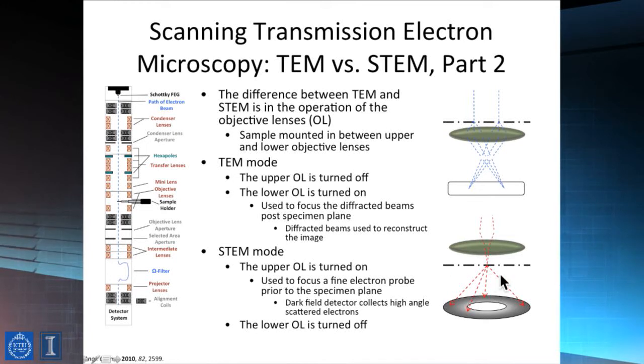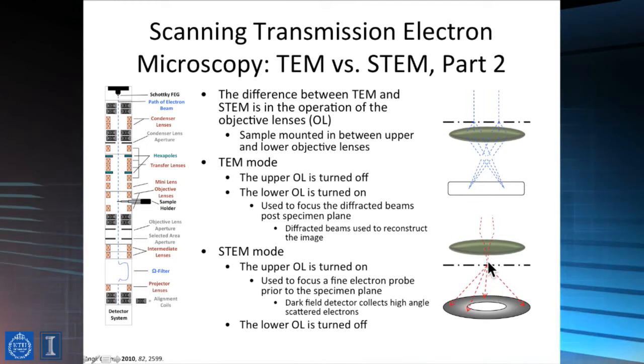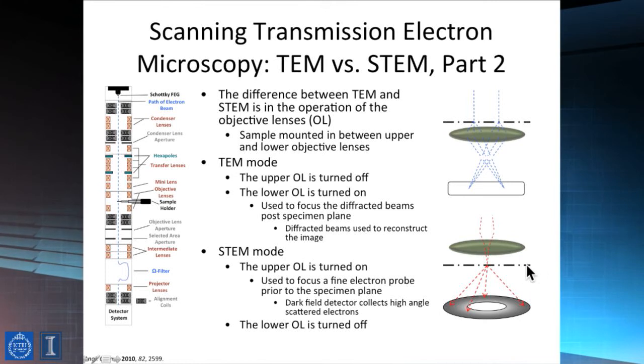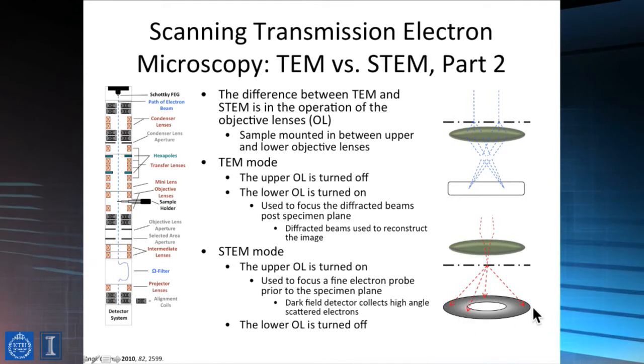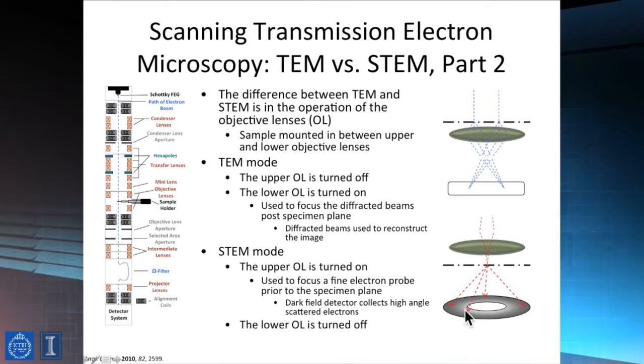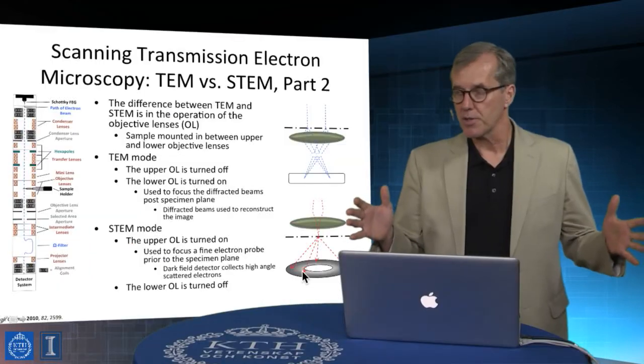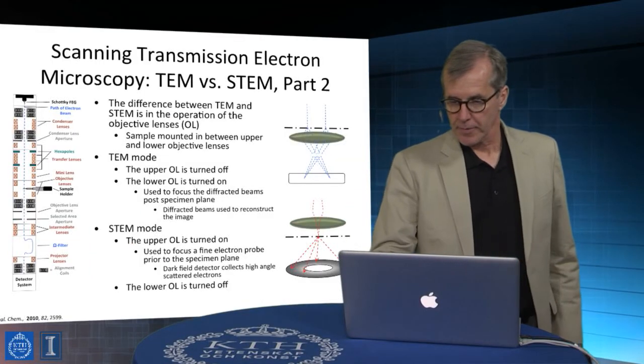And actually, the other part is that we use the electron-atom interaction as a way of acquiring an image, which comes from Z contrast associated with electrons interacting with nuclear charge and being deflected at large angles. So that's shown here in this cartoon as electron trajectories that are impacting an annular detector having scattered at a large solid angle. Okay.